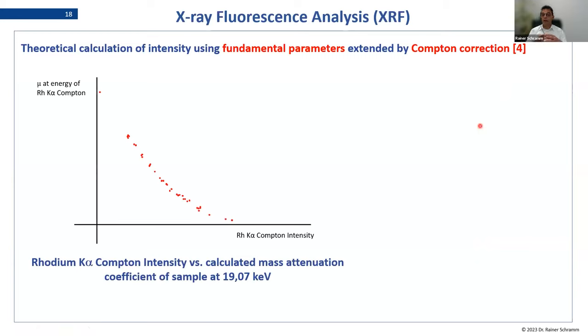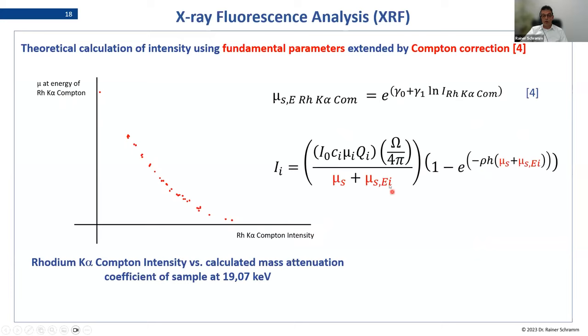I told you that the scattering of the Compton is depending on the whole sample. And then what could be done is an empirical calibration between this Compton peak with a lot of standard materials to the mass absorption coefficients of the whole sample at the Compton energy line. And this was described already a long time ago. So in this way, you could then better describe the mass absorption coefficients in this fundamental parameter equation. And in this way, also to include elements you can't measure.